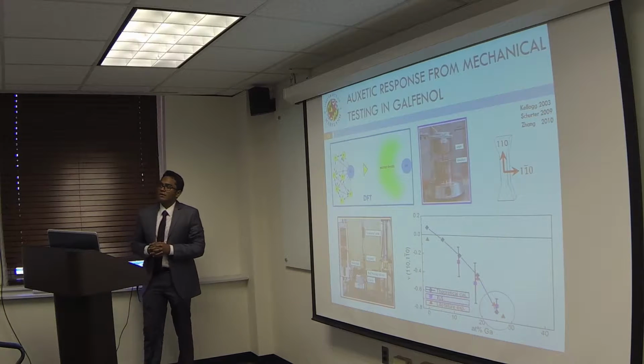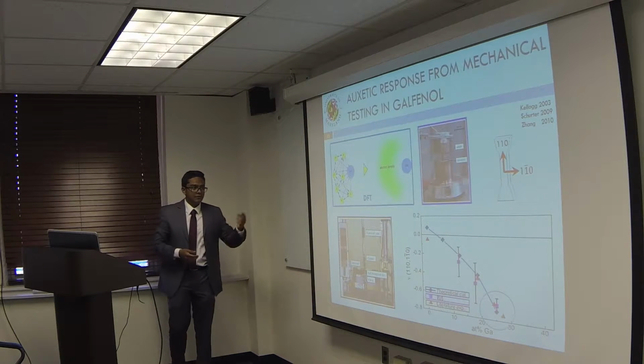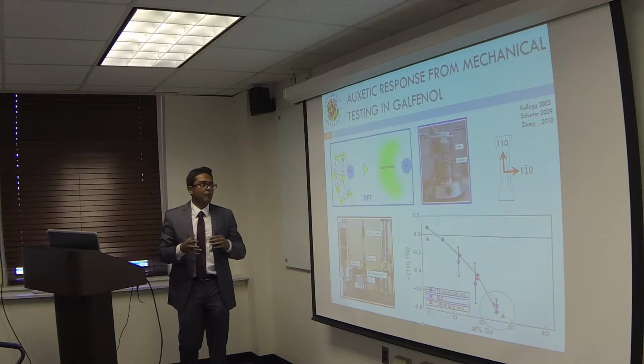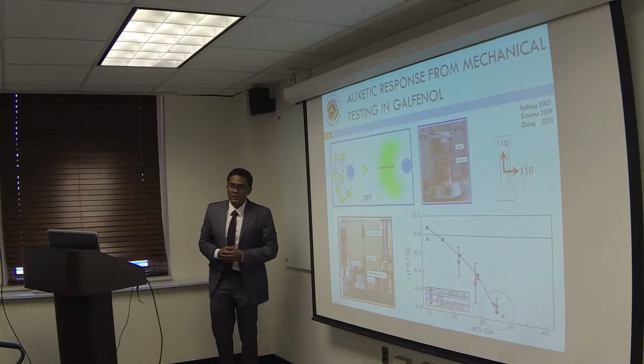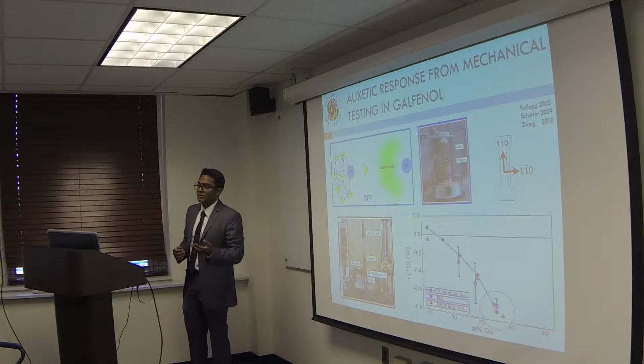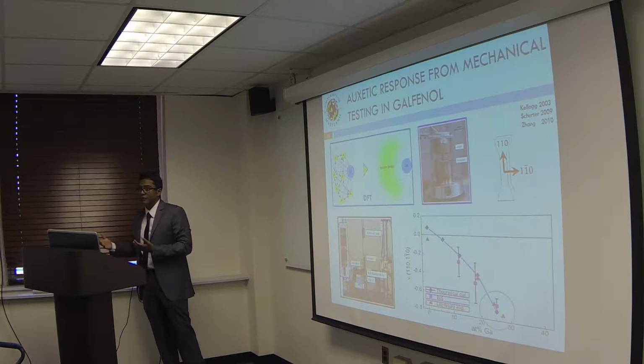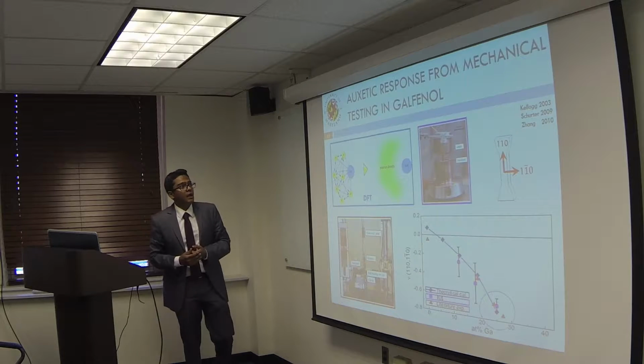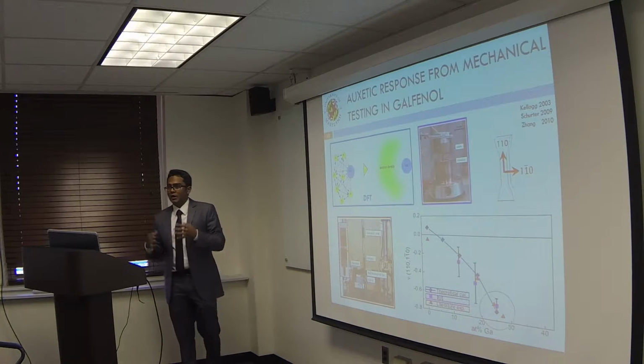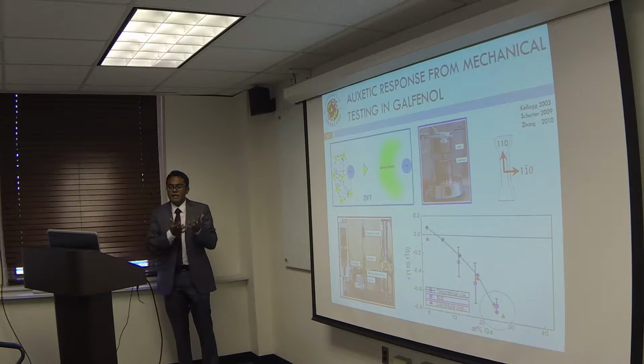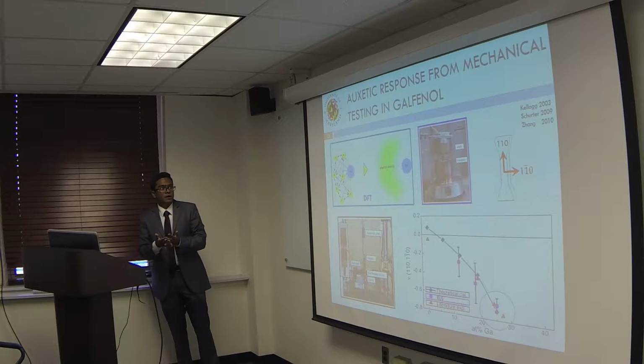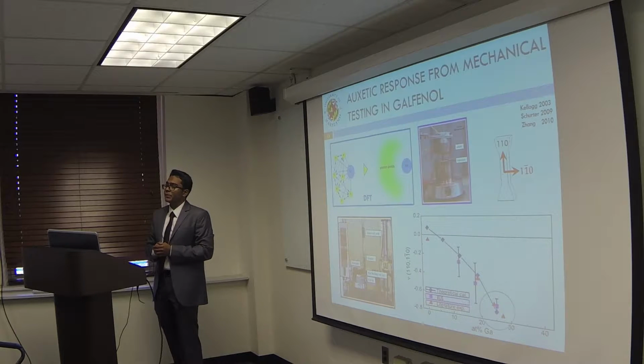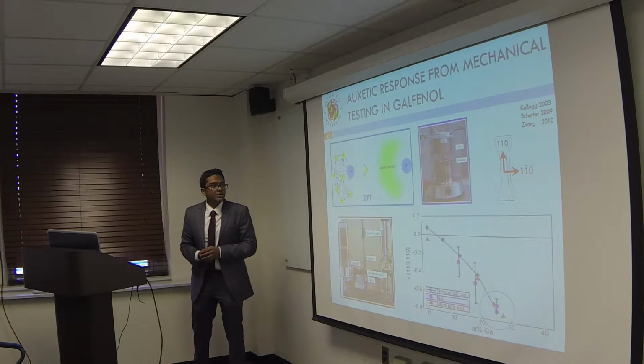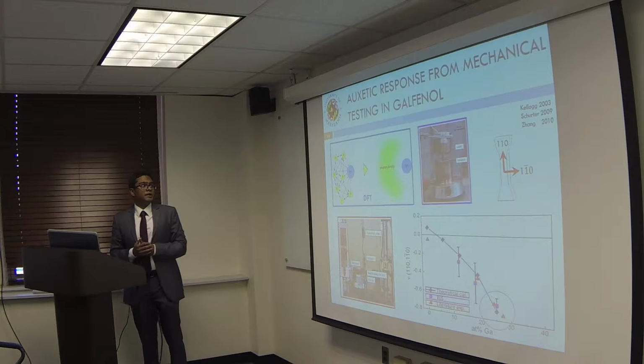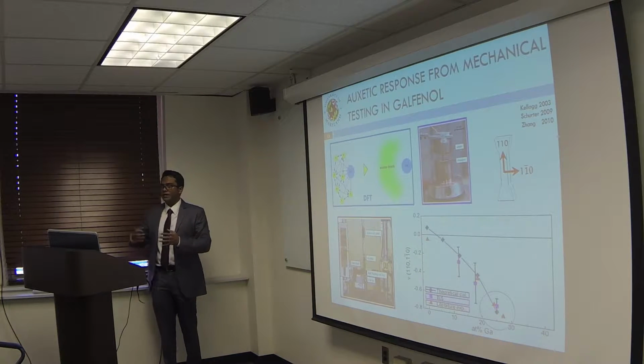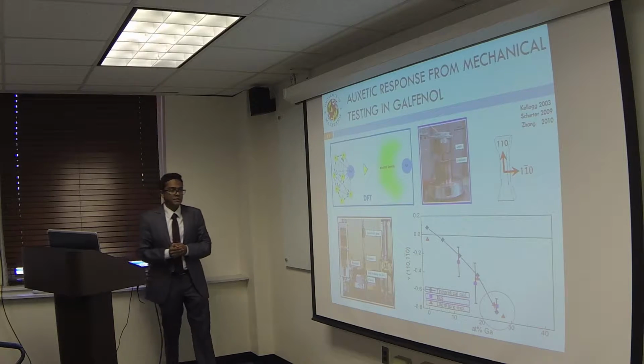Ever since Rick Kellogg discovered this effect, Dr. Flatau has had several grad students look at this behavior using different protocols. We had a previous grad student, Holly Schurter, who measured the value of Poisson's ratio using tensile testing in different compositions of Galfenol at varying gallium content. We also had studies which predicted the values of Poisson's ratio using the elastic modulus that you get from resonant ultrasound spectroscopy. And our collaborators at UC Irvine have developed a density functional theory model which could predict the values of Poisson's ratio for the different gallium compositions.